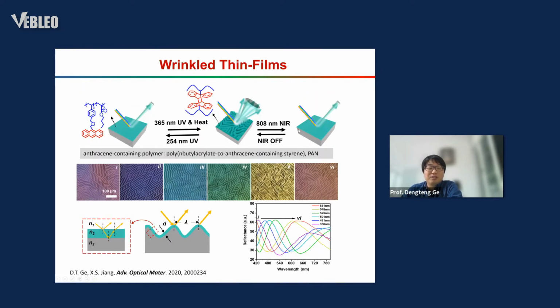So here we use this mechanism. First we generate the structure color by the thin films. They interfere from the two surfaces of the thin film, and we can make larger wrinkles. This wrinkle has scattering properties. So combining the thin film interference and the wrinkle scattering, they can generate uniform colors. In this research, we use a UV curable polymer coating on the surface to control the thickness of the coating. We can generate different colors, and under UV curing and heating, because of the gradient modulus and the thermal expansion of the substrate, the coating can spontaneously generate wrinkles.